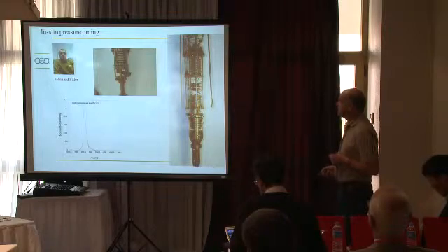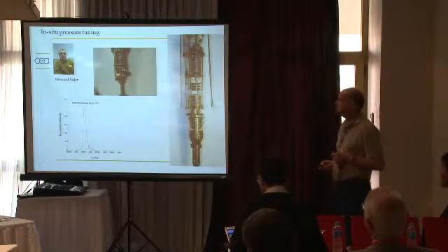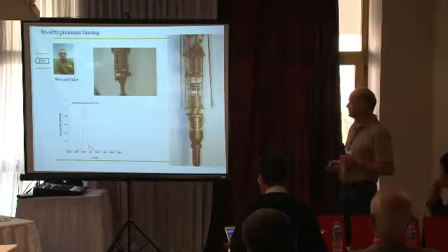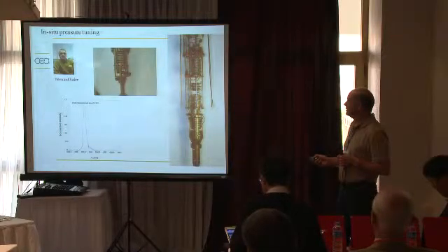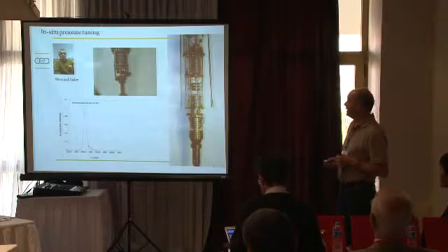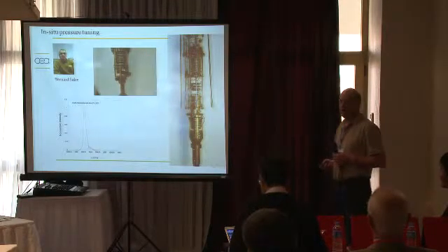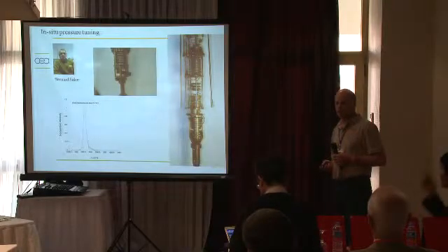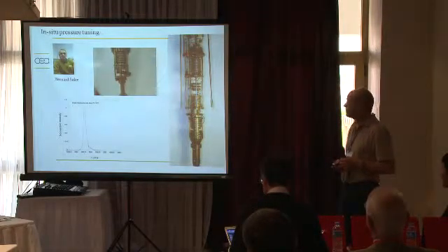Another important aspect has been the possibility to actually change the pressure at low temperature. This is the work mainly of Bernard Salce, who's developed a very effective technique using a helium bellow and a lever system to be able to change the pressure in the diamond cell at low temperature. Now Bernard set this up on a very simple helium-4 bath cryostat, which has produced an enormous amount of results on phase diagrams in many systems.